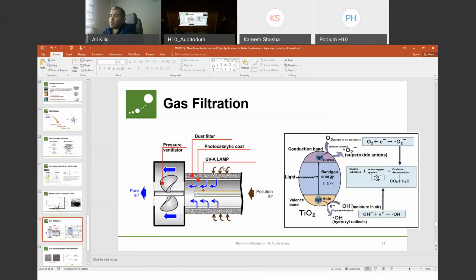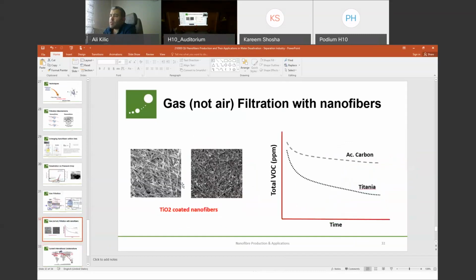And again, a similar structure might be used. Photocatalyst, I already mentioned this mechanism. This is also used to remove any kind of odors, any kind of VOCs in the air. So we are using nanofibers again for these structures. For gas filtration, these titanium dioxide coated nanofibers are quite useful materials. Regularly we use activated carbon, as in the case of water filtration, but if we go for titanium dioxide, we can easily reach better VOC removal rates.